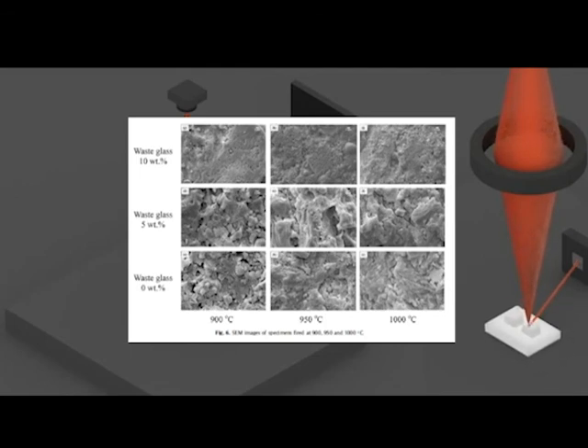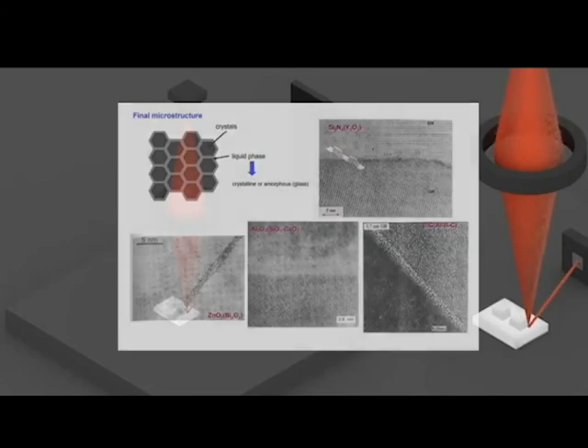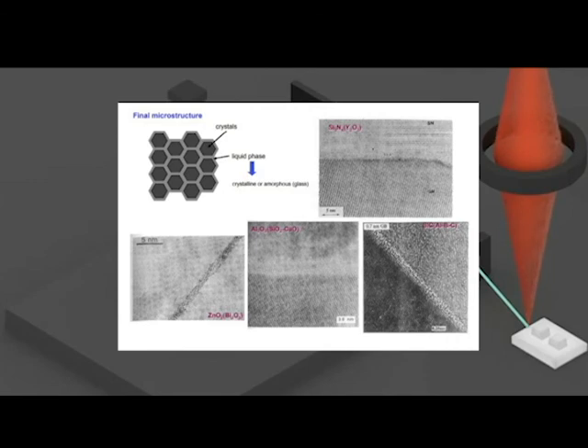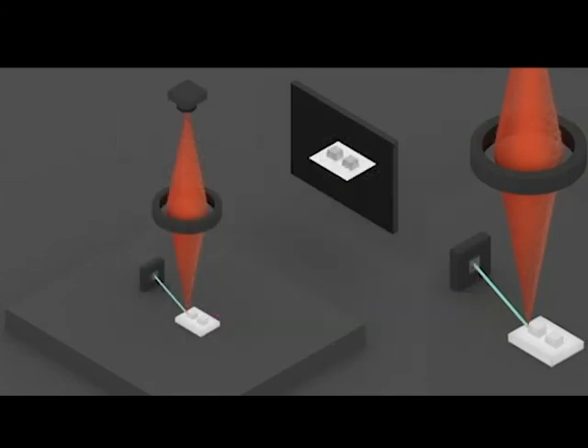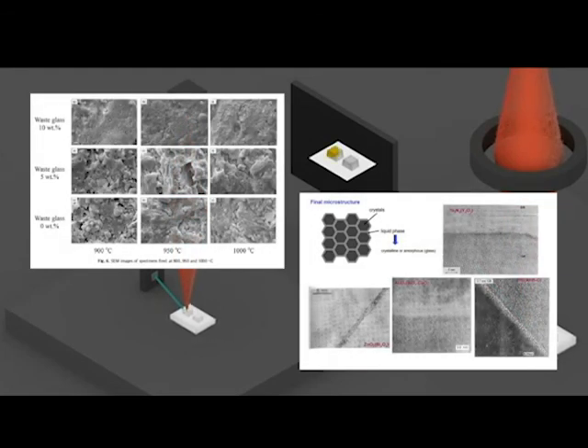As part of the clay was replaced with waste glass content, the risk of strength reduction due to quartz transformation is reduced. Moreover, the waste glass addition is glassy in nature and shows glassy phase of transformation in the body. Therefore, the addition of waste glass makes a positive contribution to the strength of the fired clay body. The liquid phase of glass fills the voids in the specimens and increases the adsorption of the particles, resulting in a more compact polycrystalline form. The image shown is how it is described.